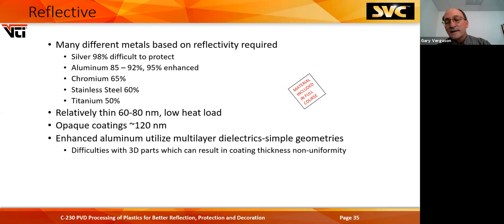All of these have slightly different colors, and automotive stylists are some of the persnickety-est people you'll ever run into. These coatings are relatively thin, 60 to 80 nanometers, and it's very low heat load. They're opaque at about 120 nanometers. And we talked about the enhanced with the dielectrics.